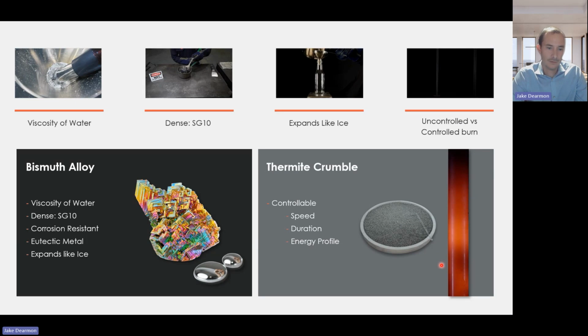In addition to the low viscosity and the high density, bismuth alloys have probably the most valuable property in that they expand when they go through the phase change. So bismuth is one of the rare metals that actually expands volumetrically between a liquid and a solid. And we're all familiar with that property in water. So when we leave a Coke can in the freezer overnight and it explodes, that's because the water is expanding roughly 9% volumetrically between a liquid and a solid. Now, pure bismuth is around 3%, and alloys of bismuth are even less. But that volumetric expansion through that phase change is what we're relying on to actually form that seal.